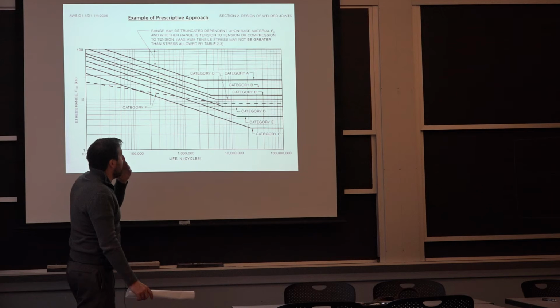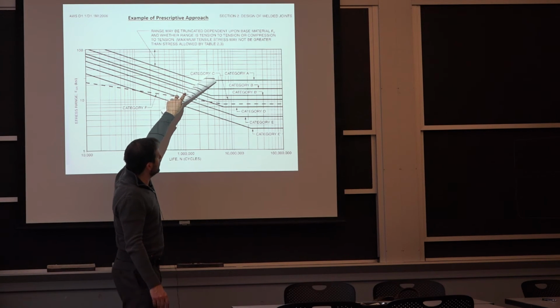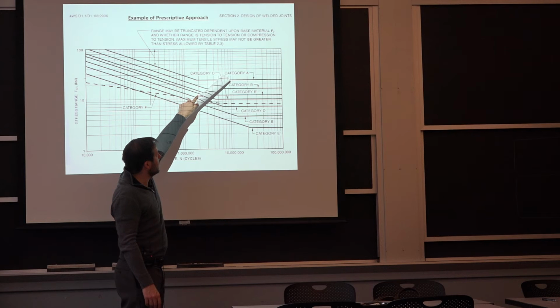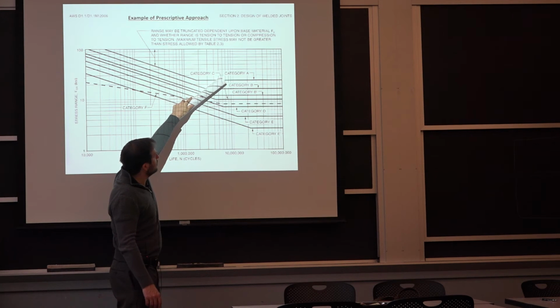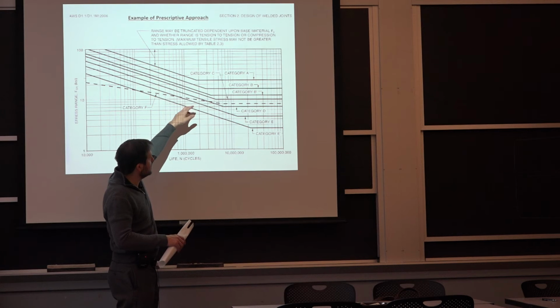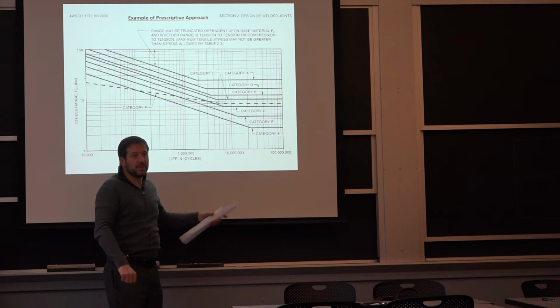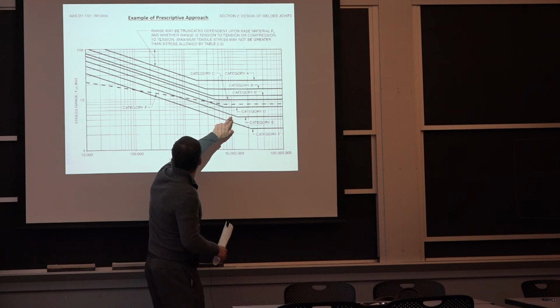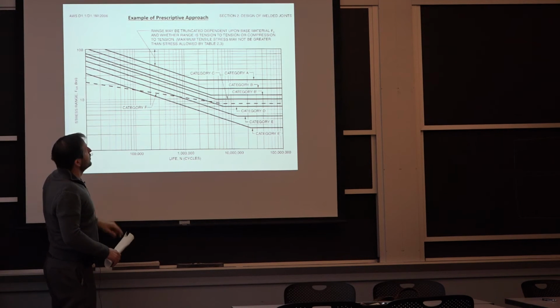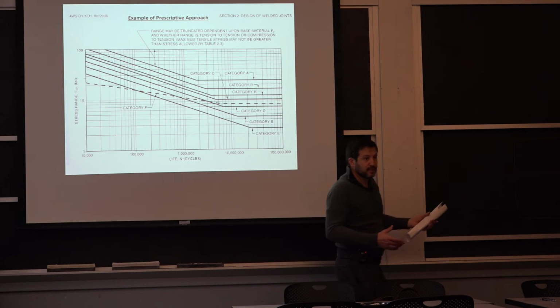We have the amplitude of the stress and then the time it takes to fail. And what you see is different lines here for different geometries of welded joints. If you don't have a weld, that's a category A here. It's a very, very high strength. But as you go into a joint that's even loaded primarily in shear, you become into these category B, C, D. And the one that has the weld perpendicular to the direction you load is typically a category E. So E here, you are at only 5 KSI as opposed to 20, 25 KSI for plain joints. It's a very, very large reduction in strength. For aluminum, it can be as low as 2 KSI.